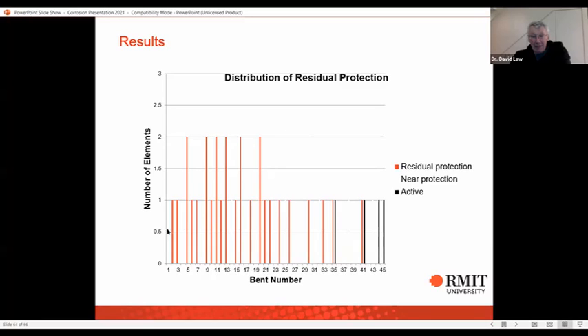The other thing that we noticed is along the length of it. This would be the more landward side of the structure. So the land is here, and this would be the more exposed to the tidal action at the end, because this is where, going out to the end of the dock, we start to go out of the harbour towards the edge of the harbour. And you can see here, these are where we saw most of our failures. And this would suggest that in the more environmentally exposed, more aggressive regions, we lose that protection very quickly, or we don't even see it.